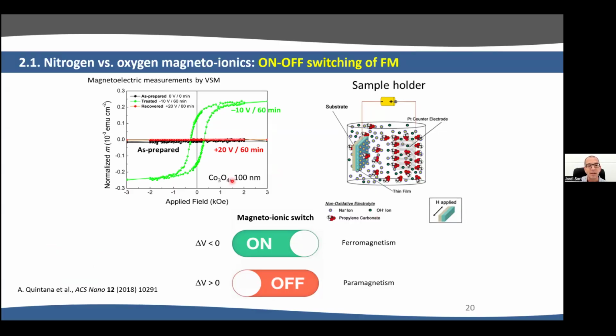This basically is what happens in a thin film of 100 nanometers of cobalt oxide produced by atomic layer deposition, that initially is paramagnetic. So as prepared, this is the black curve here. There's no hysteresis loop, non-magnetic. And one of my PhD students, Alberto Quintana, applied for 1 hour a voltage of minus 10 volt. And he could observe that after waiting 1 hour, if you measure, you can see a clear hysteresis loop.